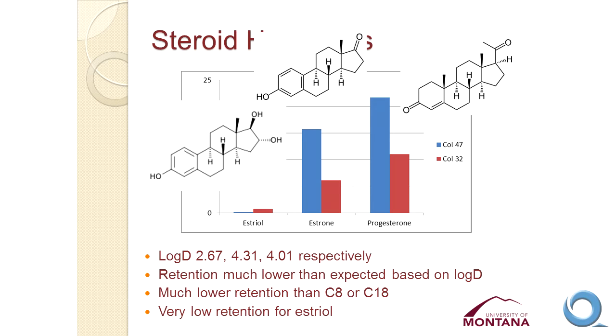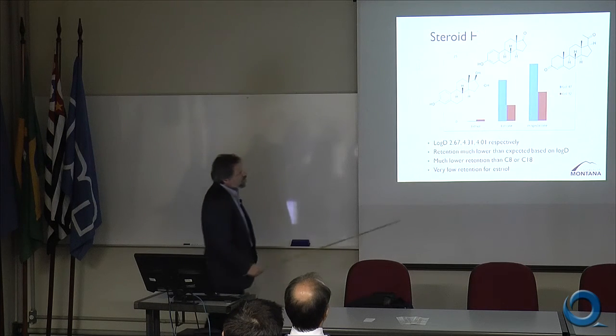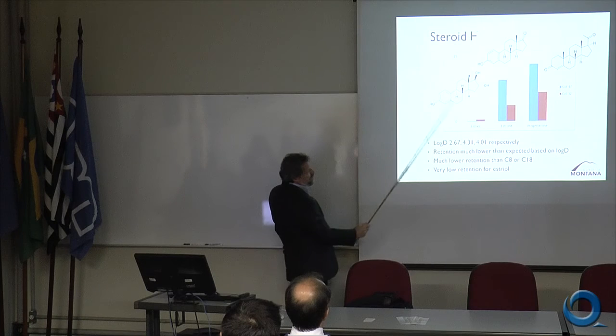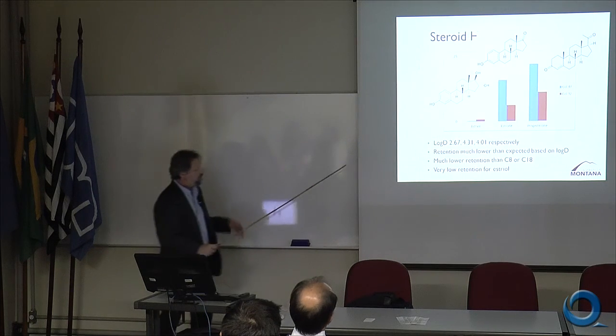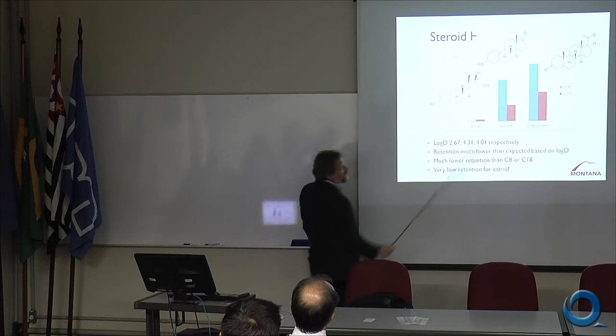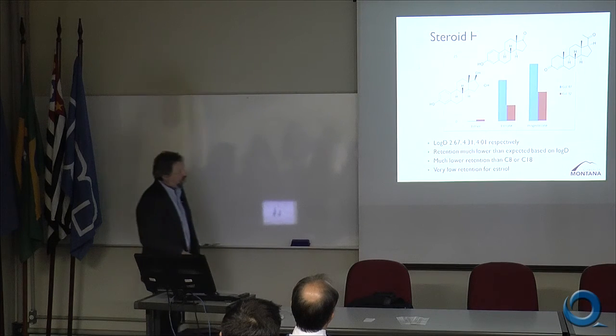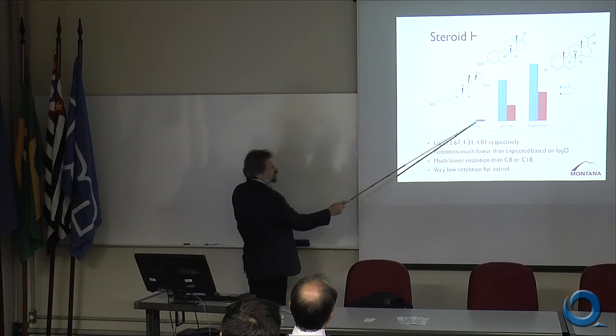And estriol, the one compound here, is extremely low compared to the others, and it's really not particularly clear why. These are the structures of these compounds, and the one thing about estriol that's different from the other two is that it has hydrogen bonding, polar groups on both ends of the molecule, whereas these molecules do not. And so it may be that that is the deciding factor here, but for some reason, estriol has very, very weak interactions with our nanoparticles, and this turned out not to be a suitable application.